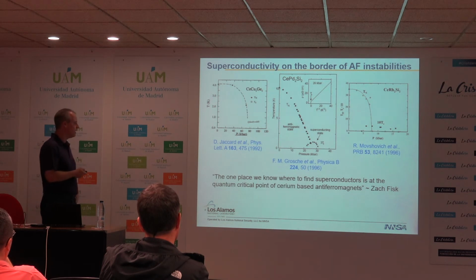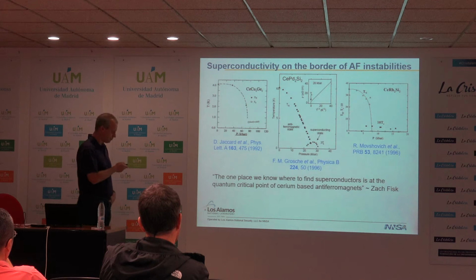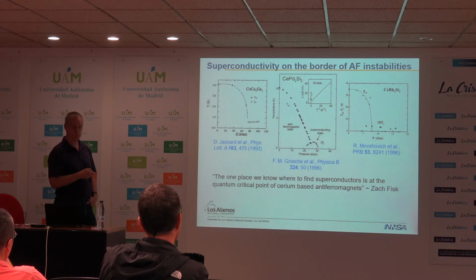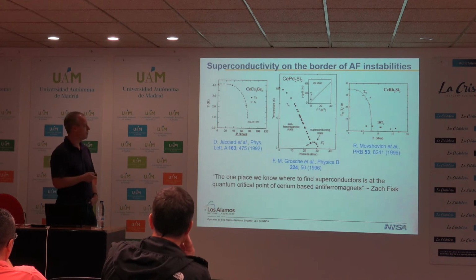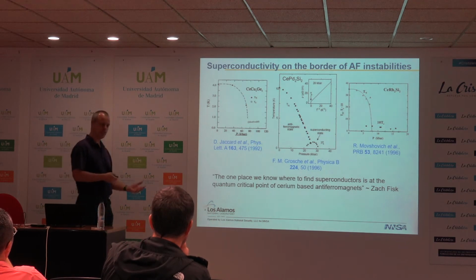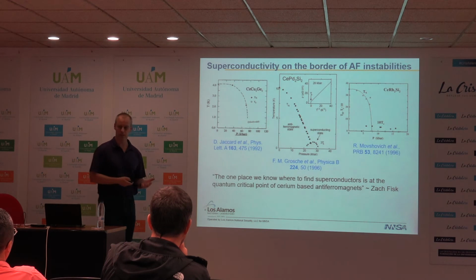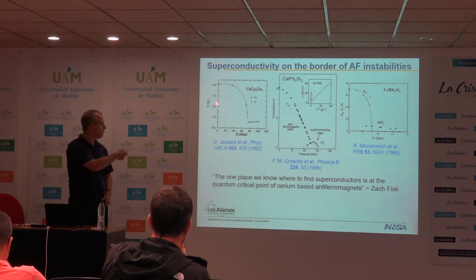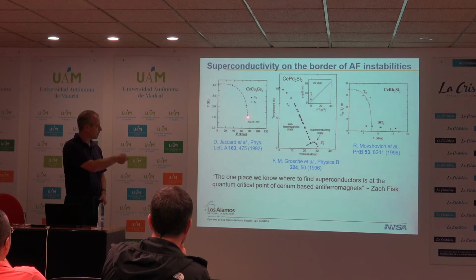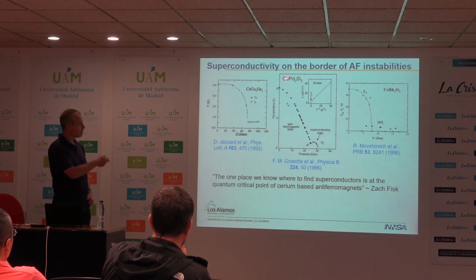So then in the 90s, people started to realize that in fact the superconductivity in these heavy fermions, particularly the cerium-based heavy fermions, seem to be tied closely to magnetism. And so these phase diagrams, now temperature is a function of pressure. Because of the small energy scales, you can easily tune the ground state of the system with pressure, so you don't need doping. And what you see is that the antiferromagnetism is suppressed, and you recover a dome of superconductivity, cerium copper 2 germanium 2, cerium rhodium 2 silicon 2. And most famously, in the work by the Cambridge group here, you see cerium palladium 2 silicon 2.